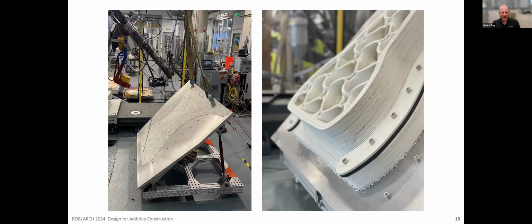So this is a picture of the build plate. Obviously, the larger the print, the more polymer volume you put out, warping and cracking are a bigger issue. Right? A little bit of glue on a regular, nice textured PEI build plate, those will get you pretty well on your normal size prints. When you start to move up to something this big, you have adhesion issues.